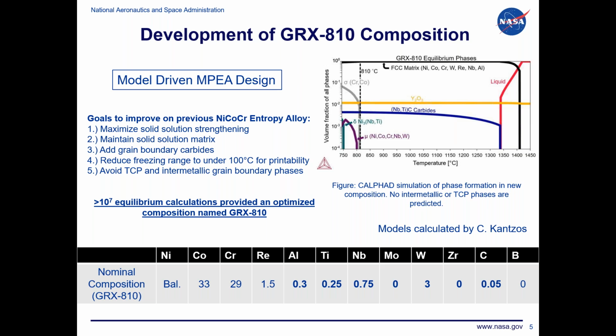The first was, how can we maximize the solid solution strengthening of the alloy while maintaining the solid solution matrix? We didn't want phases popping in and out as you 3D printed it, heat treated it, or used it in applications. We knew we needed to strengthen the grain boundaries. At really high temperature, your grain boundaries begin to act like defects, and a lot of your failures will occur along them. And so if we could add stable grain boundary carbides, we would suspect it would help improve our high temperature properties.